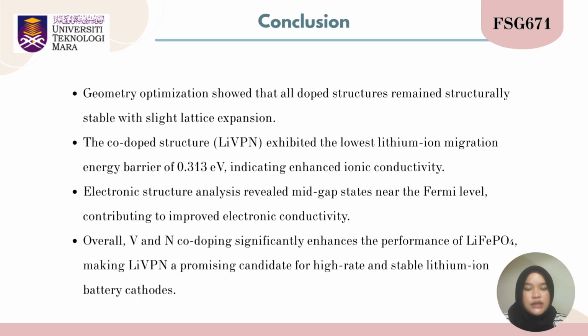As a conclusion, geometry optimization shows that all doped structures remain structurally stable with a slight lattice expansion. The co-doped structure, LiVPN, exhibits the lowest lithium-ion migration energy barrier of 0.313 eV, indicating enhanced ionic conductivity. Electronic structure analysis revealed mid-gap states near the Fermi level, contributing to improved electronic conductivity. Overall, the vanadium and nitrogen co-doping significantly enhances the performance of LiFePO4, making it a promising candidate for high-rate and stable lithium-ion battery cathodes.